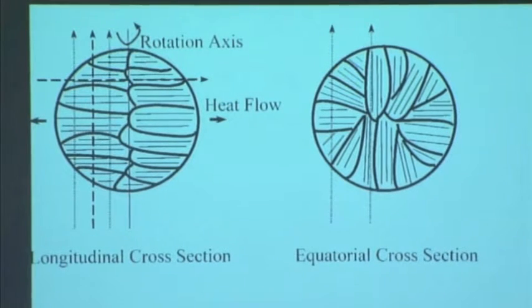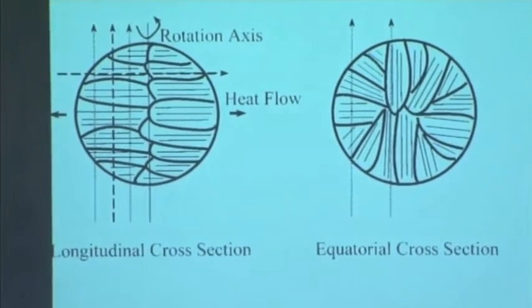And one of the primary criticisms is that even though this might be occurring, and there is some evidence from meteorites that are thought to be planetoid cores, that this kind of solidification is occurring. One of the arguments is that after the solidification, there's deformation, and that deformation is going to tend to obliterate whatever was present during solidification.